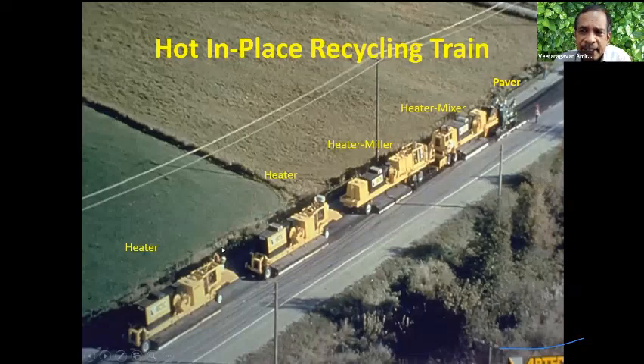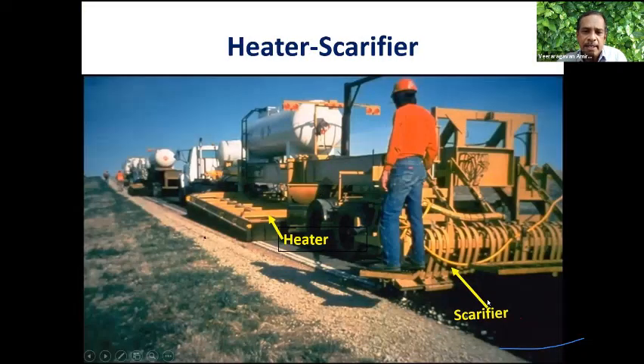So what I try to do here is that it is like an equipment train. I heat the material, then I mill the material, I mix it with the virgin aggregate and pave it back. So, all in one operation. A heater, scarifier, and a pug mill, and that material is laid. So when the equipment train moves by 1 kilometer, you have a newly laid pavement.